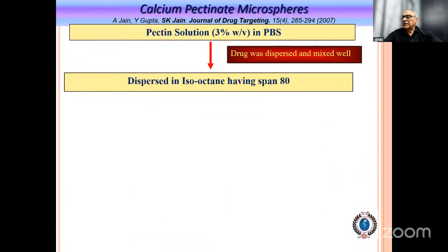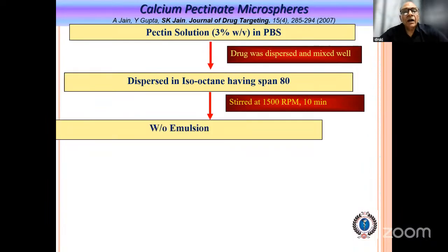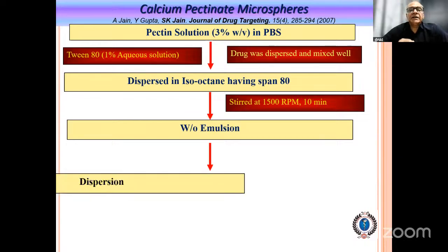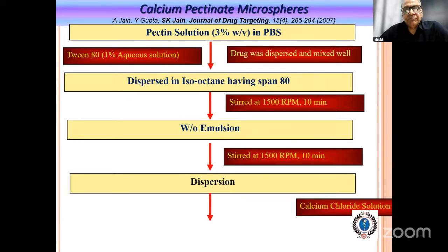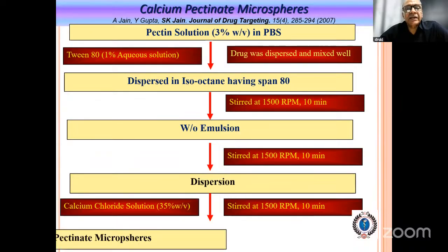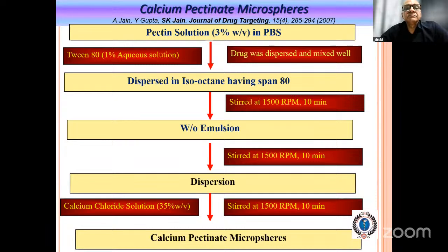This is about the studies on the microspheres that we have prepared using pectin as a polysaccharide polymer, right? It's a biodegradable pectin we have used. We have prepared calcium pectinate microspheres. The pectin is dissolved in PBS, and the drug was added, dispersed and mixed well in the pectin solution. And this pectin solution is dispersed in isooctane, having Span 80 as an emulsifier, right?